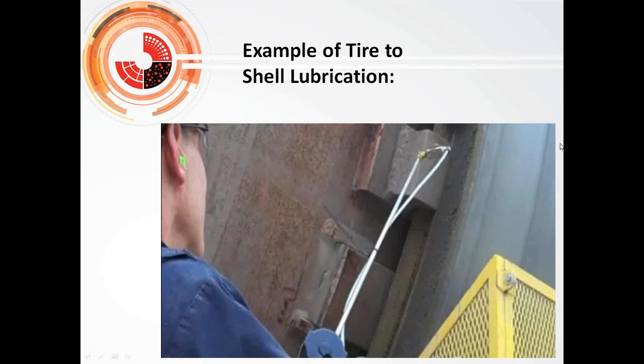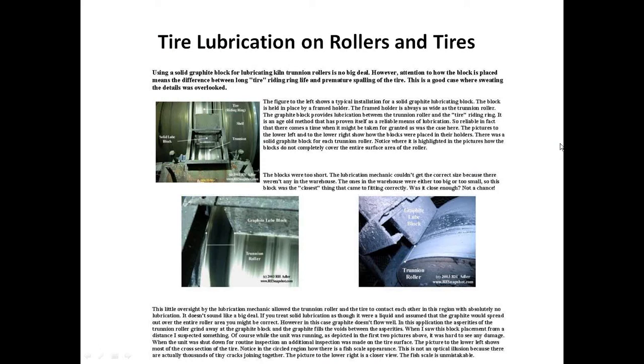And then on the side of the tires, you can't do this, so you can use a spray type system to get lubricant between the stop blocks and the tire. You can also use this on the bore if you don't want to put blocks between the tire and the shell for safety reasons. Yeah, and on a dryer or dryer cooler, you usually don't have the temperature to melt the blocks, so you need to use a spray system to lubricate the ID on the tire. What you don't want is a lubricant that picks up dirt and dust. It's a metal type lubricant with an emulsified carrier. When you spray it on, you've got to get rid of anything that can cause dust or dirt to get in that bore, because obviously it's not a good idea.